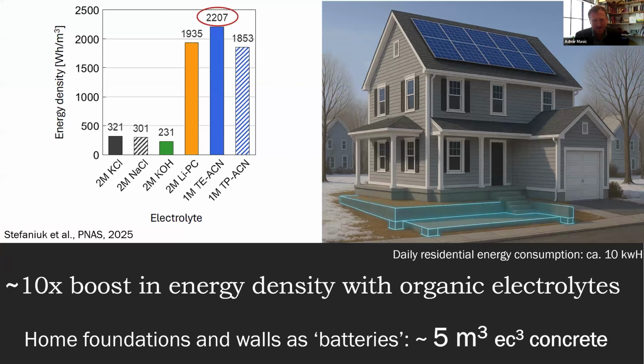So we actually improved that significantly recently just by changing the electrolyte. If you go away from water-based electrolytes, where the water splitting limits our performance to 1 volt, you remember that 1 volt is each unit cell, and it's 1 volt because of the water splitting potential at 1.3 volts. So we always keep that voltage low. But here, just by extending the voltage through other electrolytes different from water, we hit 2000 watt hour per cubic meter, which then translates in only 5 cubic meters of EC3 required in the foundation to satisfy 10 kilowatt hour daily need.